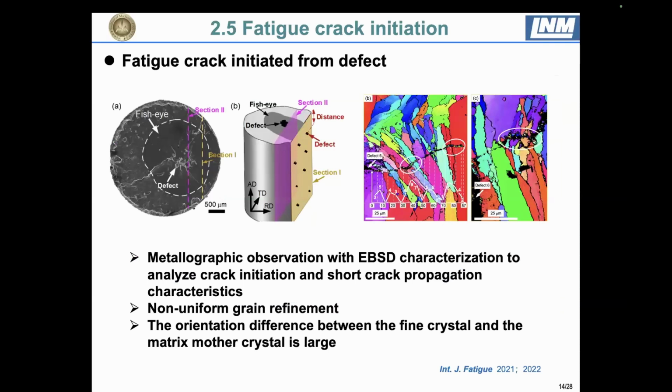Of course, we also cut the section perpendicular to the fatigue surface and tried to do an EBSD analysis. We found a lot of multiple cracks along this section, and this is a crack initiation site.